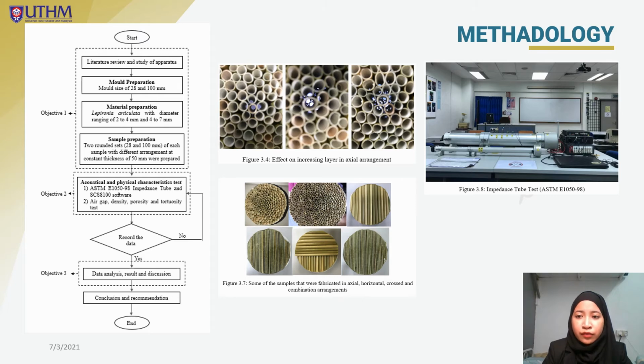As we can see here, the flow chart shows the process of this research. In this study, 4 different arrangements of samples, namely axial, horizontal, cross, and combination, were assessed. The diameters used for each arrangement range from 2 to 4 mm and 4 to 7 mm respectively. This means there are 2 different ranges of diameter of Lepironia articulata for each arrangement. In the axial configuration, 3 different lengths were cut, bonded together and arranged in an overlapping manner. As seen in figure 3.4, increasing the number of layers makes the path more intricate.